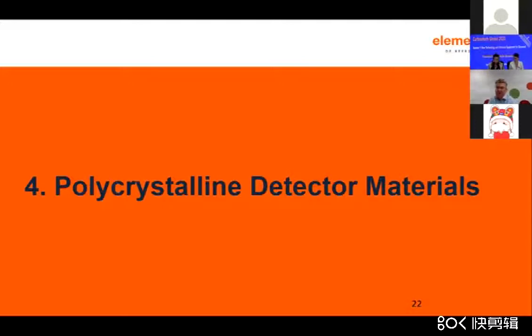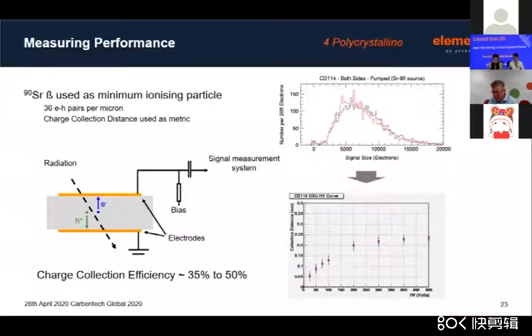So what kind of materials have we developed? What was the journey that we went on? Well, the first material that we really developed was a polycrystalline detector material. And again, it's interesting to work out how we actually characterize this material. You're using a controlled beta source which has a known charge generated in it. And then you look at that charge that's generated and try to see how much of it you're collecting.